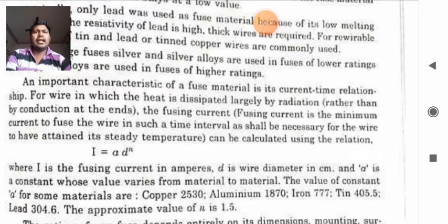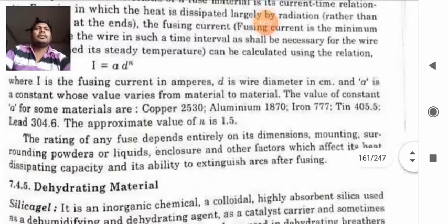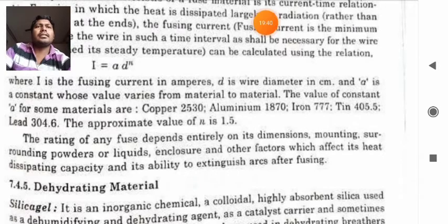So what is this I? As I told, it is the fusing current in amperes. D is the wire diameter in centimeters, and A is the constant whose value varies from material to material. The value of constant A for copper is 2530, for aluminum it is 1870, for iron it is 777, for tin it is 405.5, and for lead it is 304.6. The approximate value of n is 1.5.